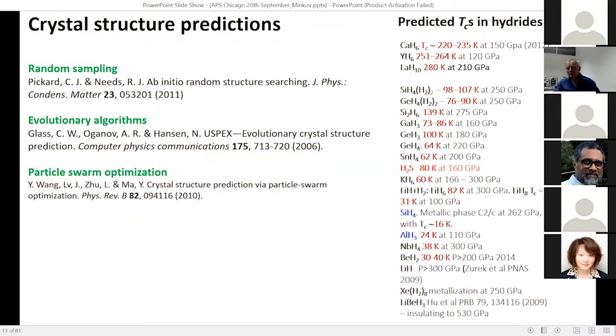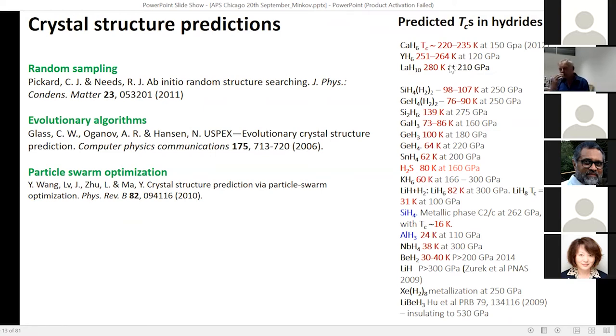Fortunately, at the same time there was dramatic development in crystal structure prediction methods, which made it possible to predict many substances. Once a crystal structure is known, it is relatively easy to calculate phonons, electron spectrum, and superconductivity — because the superconductivity here is conventional, following BCS. So there were many predictions, including calcium hydride with very high critical temperature.